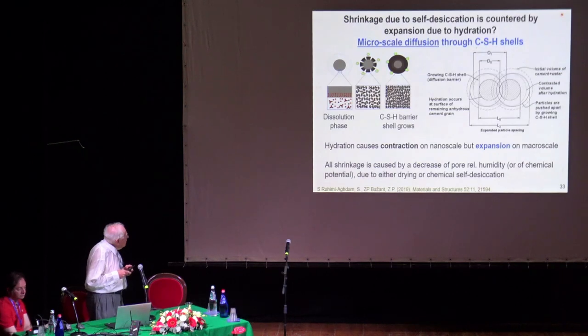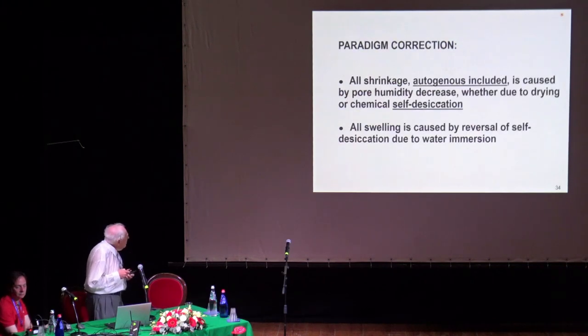From this it can be understood that hydration is always expansive. Most people don't believe this. They say hydration causes shrinkage. Yes, it was determined by Le Chatelier in 1880 that the result of the reaction of anhydrous cement and water combined is a slightly smaller volume, a fraction of a percent, than the original. Yeah, that's true, but that is not what matters for the mechanics involved. This is like a crystal growth pressure. It expands inevitably in a skeleton if it's not a powder. So this is, I would say, a correction of the paradigm.